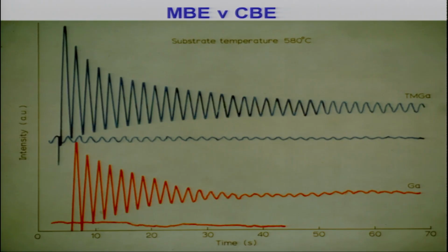Okay. A couple more things before I finish. Back in the sort of 80s and 90s, CBE became the preferred method. There were separate conferences for CBE. It died. Where's it gone to? I mean, one of the things that is curious is that if you look at a typical MBE RHEED oscillation, it dies after, in this case, about 35 seconds. You can prolong it by adjusting the conditions. But under the same conditions, the RHEED oscillations for CBE go on forever. So there's something curious going on here that we still don't understand. So there is mileage in MBE in the future. That's what I want to say. There's lots more to do.